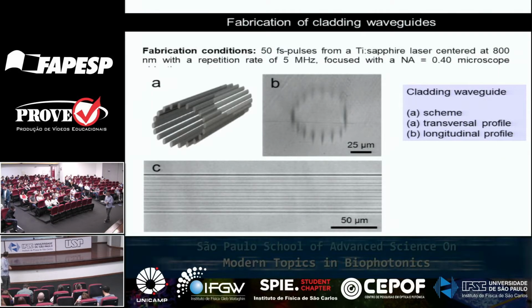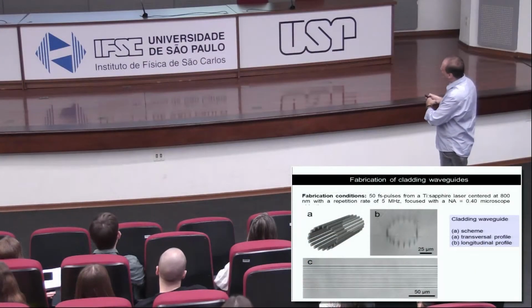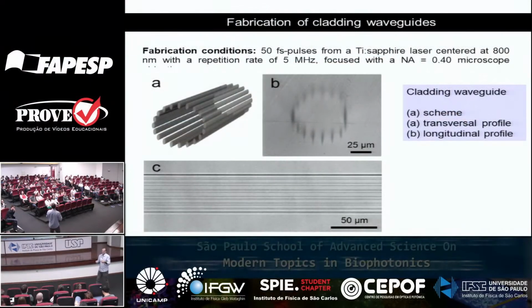Okay, that might work. However, when you try to do it the way I did with the Gorilla Glass, if you just pass the laser through in order to densify the material, in order to get guiding by increasing the index of refraction, it doesn't work for such crystals. In fact, for the amino acid, in the position where you pass the laser beam, the index of refraction actually decreases instead of increasing. So the only way to fabricate a waveguide in such a type of material is by fabricating what we call cladding waveguides. So instead of fabricating, it's much more work, because in the other case, I basically make one pass, the index of refraction increases, and I have a waveguide.